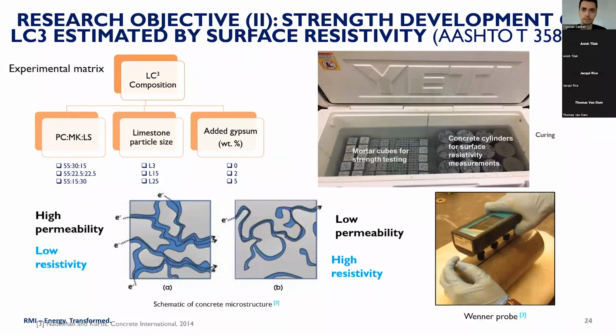To briefly mention the surface resistivity test for those who are not very familiar with it, it's a standardized AASHTO experiment. You use a probe, the so-called Wenner probe. It has 4 probes. The outer ones send an electrical current, the inner ones measure the electrical difference, and then the device calculates the resistivity automatically. The higher the resistivity, the higher the tortuosity you would expect in your concrete. But that also depends on the pore solution concentration. So if you keep the pore solution conductivity constant, for example, you can say the higher the resistivity, the better the microstructure, as shown in this schematic.